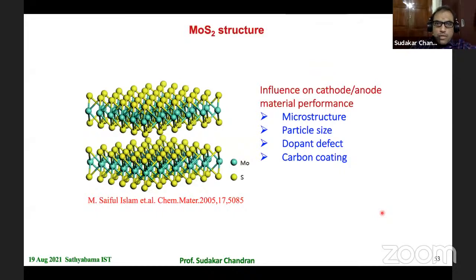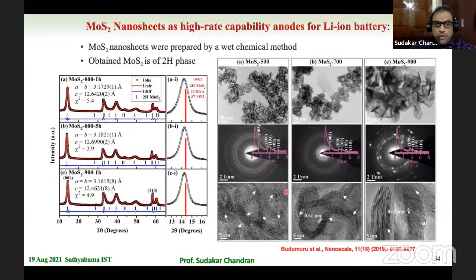So here is a typical structure of molybdenum disulfide. It's a layered structure. In each layer, you have one molybdenum layer and 2 sulfur layers, and these are all stacked and held by van der Waals force. There are various forms of it, like 2H, 3R, and 1T phase. I won't go into the details of the structural aspects, but most of the molybdenum disulfide that we studied is the 2H form.